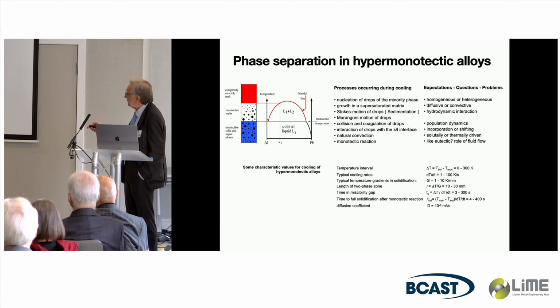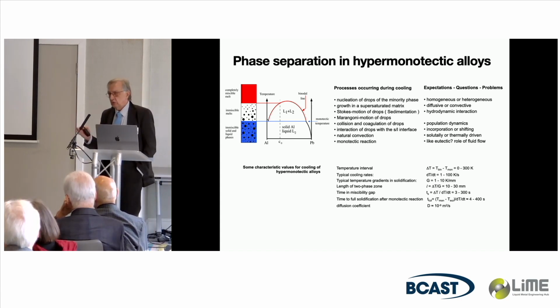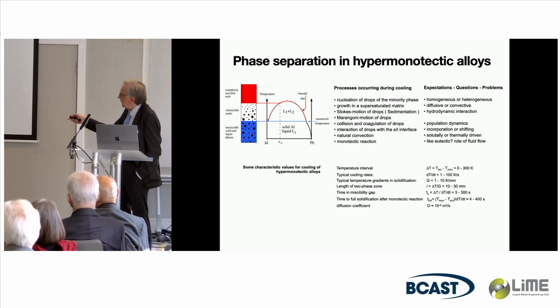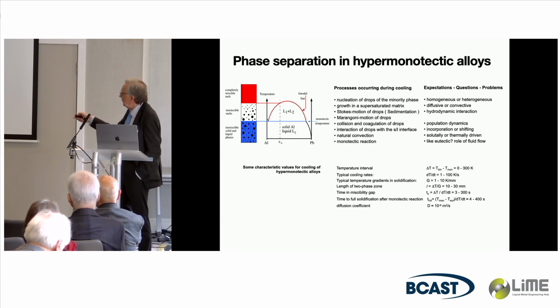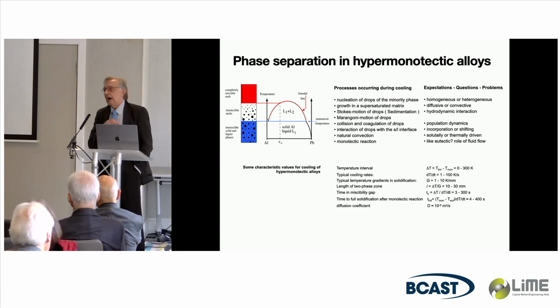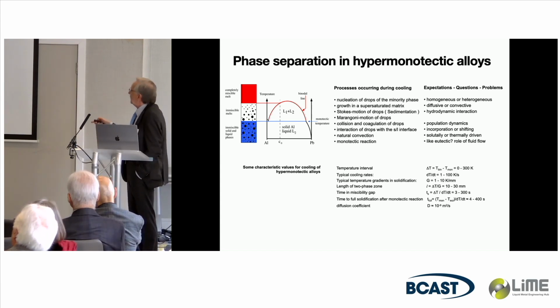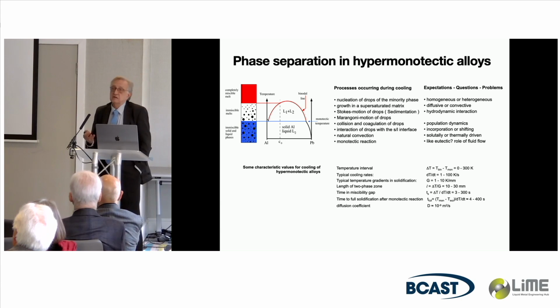Here is a real difficulty. If you have such an alloy, you cool through a miscibility gap. As I've written here, you have typical intervals for slightly hypermonotectic alloys of up to a few hundred Kelvin. So whatever you do, if it's not rapid cooling, with typical cooling rates in directional solidification, there's ample time, once you go below the binodal line, for the second phase to appear either by homogeneous or heterogeneous nucleation. They will grow, and if they grow in a supersaturated matrix, either by diffusion or convective diffusion, this liquid phase here has a possibility to do Stokes motion because it's in aluminum.